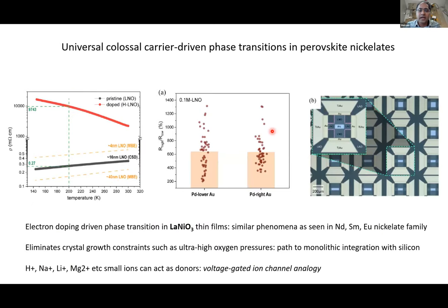And for those of you who are interested in the nickelates in particular, this phase transition actually happens in lanthanum nickelate too. So this is something we showed last year. Lanthanum nickelate is sort of an anomalous compound among the family of rare earth nickelates because it doesn't show a thermal phase transition. But then we showed that this physics of the electron doping transition is actually common, universal across the nickelates. So even for LaNiO3, the 3+ to 2+, or at least the simplistic interpretation of the electron addition to the nickel manifold is sort of manifest in the same way. You can see this metal to insulator phase transition in LaNiO3.